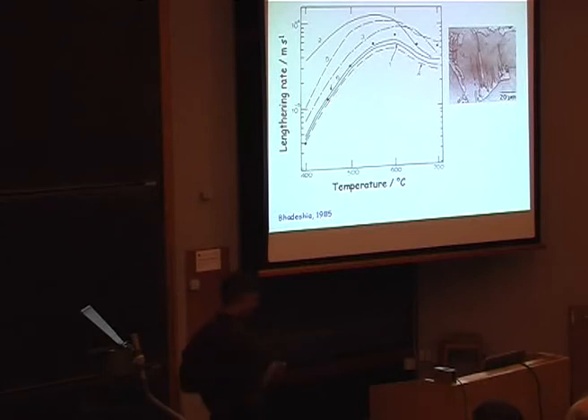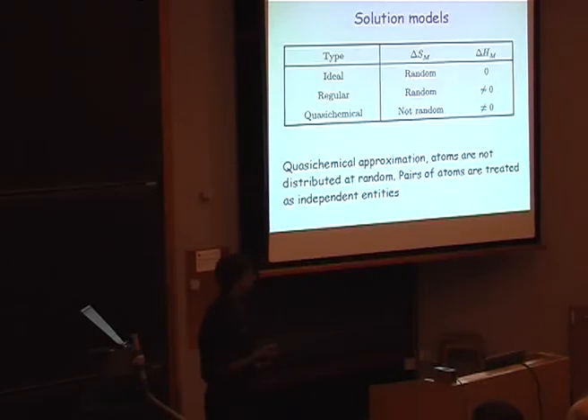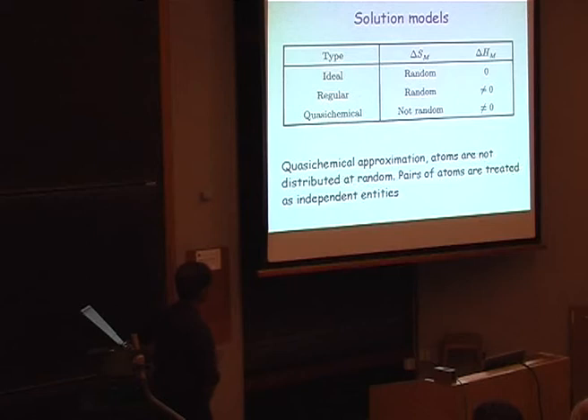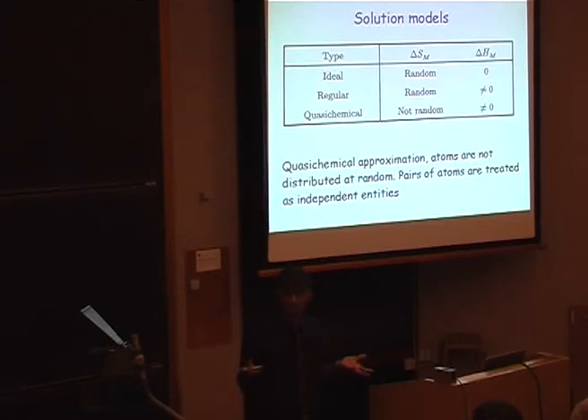Okay? And the reason why you have all these differences is that we use very elementary models in all these packages like Thermo-Calc and MTDATA and so forth, which are used for phase diagram calculations. They basically assume either an ideal solution or a regular solution where you have an enthalpy of mixing. But the entropy of mixing is treated very badly. You assume that there is a random distribution of atoms. And you can't have a random distribution of atoms if there's a change in binding energy when you mix atoms up.